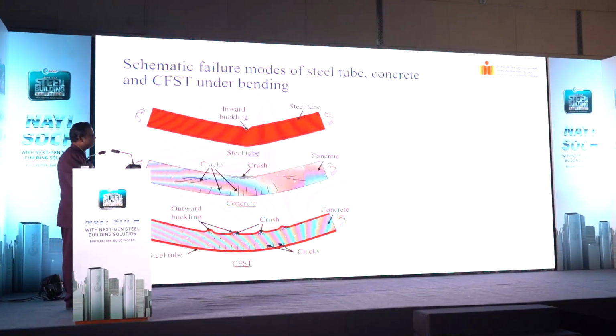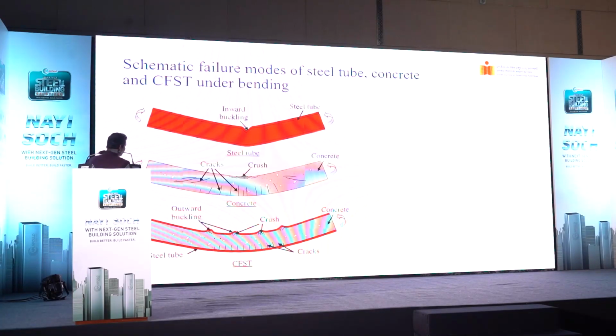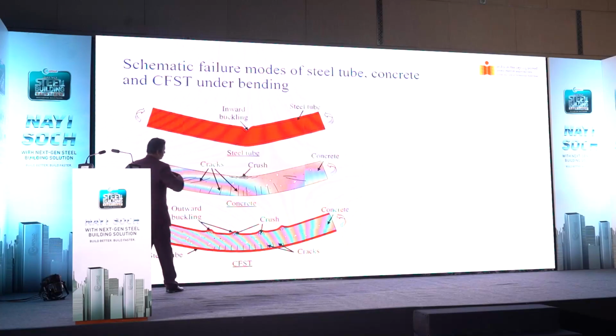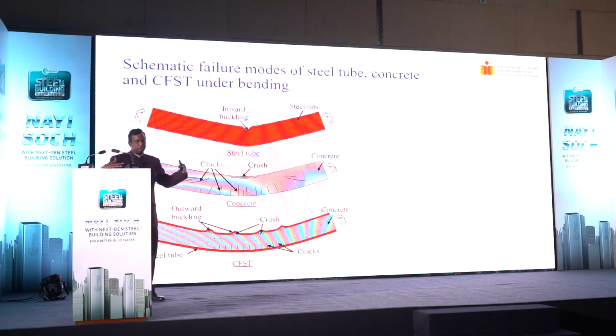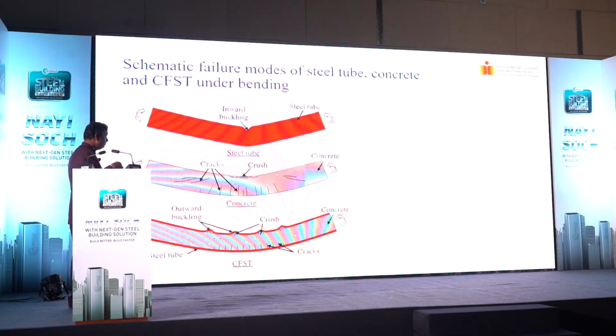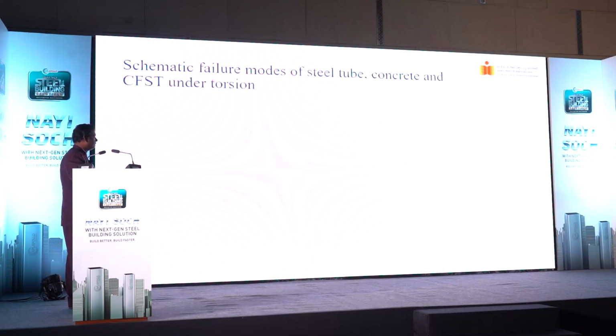And then when you have bending, what happens? Then there is an inward buckling at the top. But that is a simple steel tube. If you have concrete, it has a lot of cracks and crushing happens. But if you infill it with concrete, there is only small outward buckling, but at several locations. So the failure is sort of uniformly distributed, not a catastrophic one, which is again a desirable mode of failure.